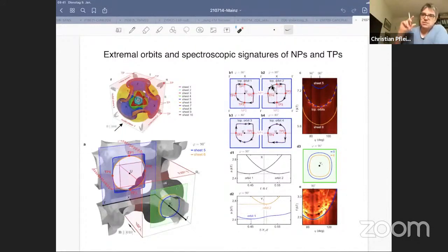And the argument goes exactly the same way I showed you for the cobalt silicon, right? It's just that you have to pick out the right orbits. And so this is this complicated Fermi surface. And now when we apply the magnetic field, this is rotated a little bit, and I'm showing you a different cut here, right? So actually this part here is somewhere here, but it's rotated a little bit. And let's suppose we apply the field along a 0, 1, 0 direction.